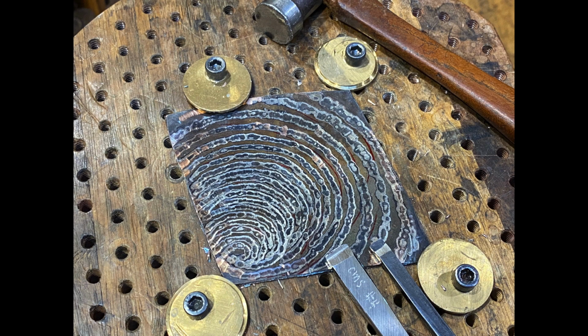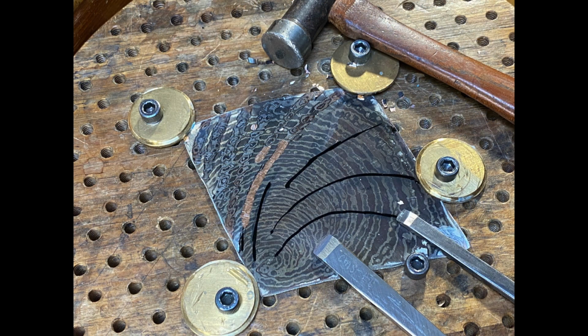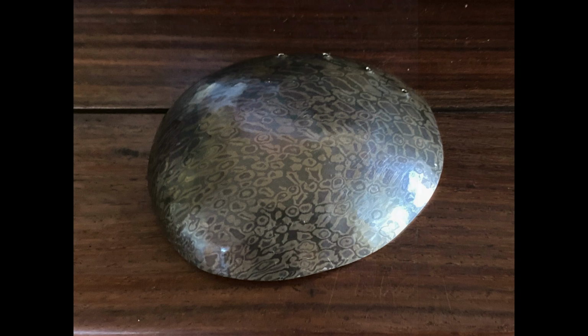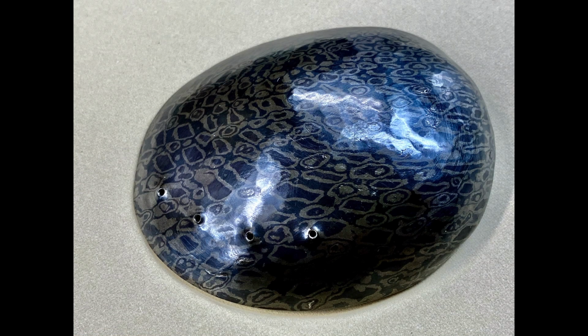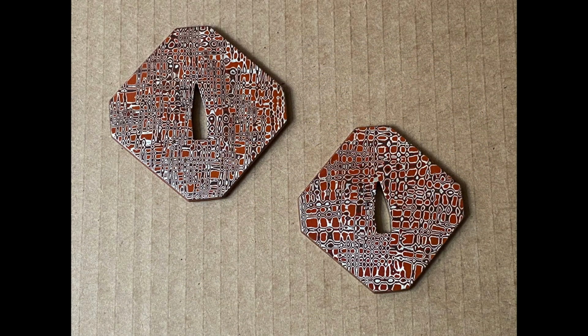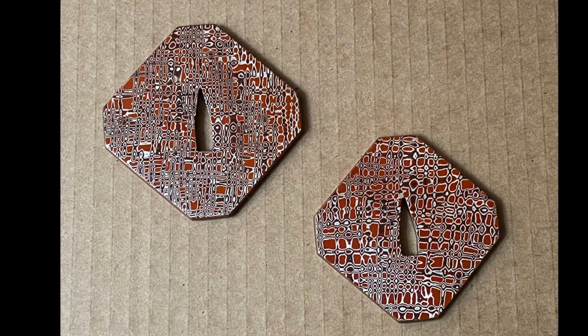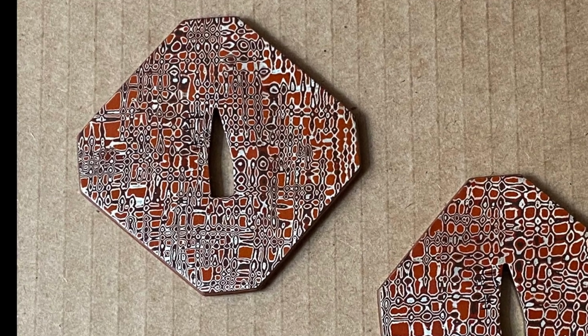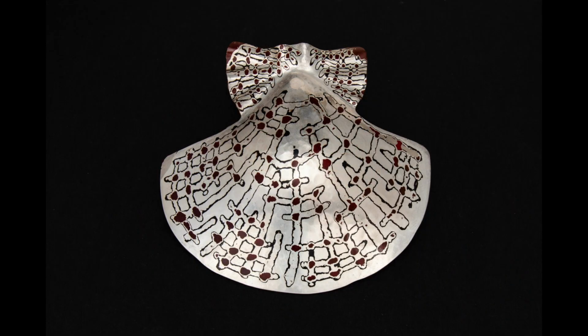A work in progress. Curved channels through dark layers were forged flat, then later cut across with slow curving channels. We see the result, annealed and pickled before being formed into an abalone shell, and the finished shell. This is my usual procedure for patterning. Channels can be tight and dense, like on these 2 Japanese tsubas, or sparse on a large field.